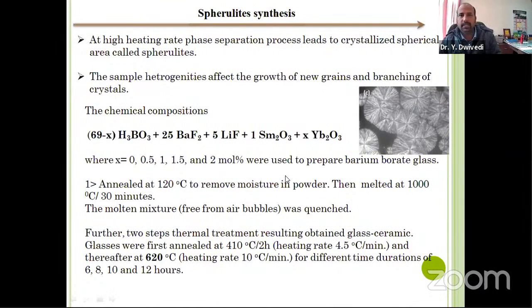So let's go for the other part, just 3-4 slides and then I will stop. As for the spherulite glass, if you heat this borate glass with a very high heating rate, some phase separation appears, and that heterogeneity leads to the growth of grains and branching in the crystals, mostly looking like this, as you can see in the image. The same thing mostly occurs in polymers, it is reported in silicon glass, and it is reported in borate as well, but for this we selected a different structure and glass composition - again we have H3BO3, barium fluoride, and lithium fluoride as well.